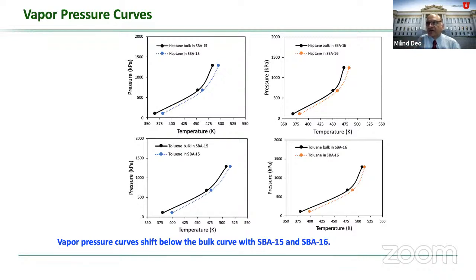We have some new DSC data that I don't have on this set of slides, where we created a technique to fill only the nanopores and leave the bulk pores alone. And that actually shows a suppressed, earlier transition compared to the bulk, and we're still trying to get our arms around what is going on there. So anyway, that is this story.